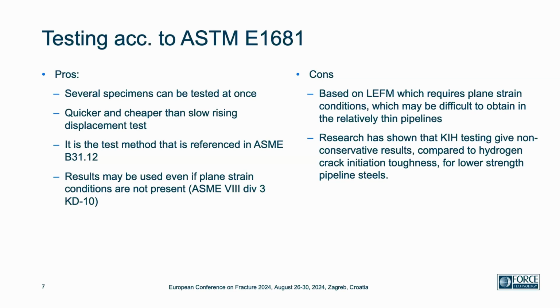The con is that it's based on linear elastic fracture mechanics, which requires plane strain conditions, which may be difficult to obtain in relatively thin pipelines. And research has also shown that the K_IH testing gives non-conservative results compared to the hydrogen crack initiation toughness for lower strength pipeline steels. The results may be used even if plane strain conditions are not present in the ASME Boiler and Pressure Vessel Code. I was surprised that it's allowed, considering that the Boiler and Pressure Vessel codes usually are conservative compared to other codes.